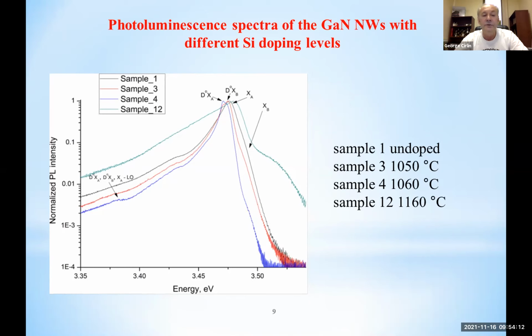So next, we are going to discuss a little bit what is happening with ultra high levels of doping of different kinds of materials, starting with gallium nitride nanowires. So what we found, for example, if we increase the number of atoms impinged from the silicon source, there is a shift of a PL line from the exciton in this particular case.